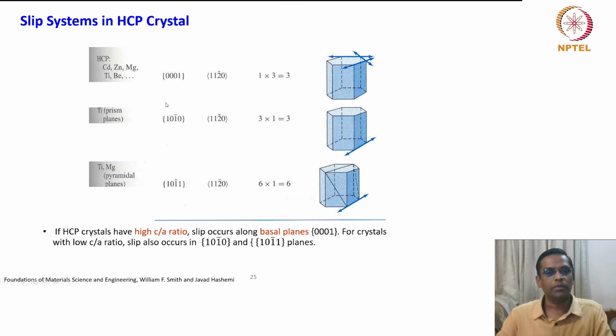Another type of slip system is the 10bar10 slip planes, and this is called the prism plane, with the 112bar0 direction. You have 3 planes like this and 1 direction, so 3 slip systems. Titanium and magnesium also show pyramidal planes, which is shown here. This is the pyramidal plane, and the same direction. So you have 6 pyramidal planes of similar direction, so 6 systems. So you see again in HCP about 12 slip systems.